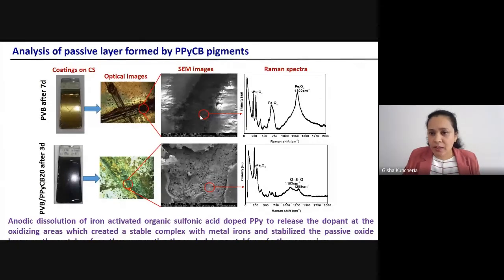Raman spectra show the corrosion product Fe3O4 for the pure coating. But coming to the conducting polymer coating, you can see there is no more Fe3O4 peak, but it shows a new peak that corresponds to the O=S stretching vibration. This O=S is coming from the dopant anion of the conducting polymer, organic sulfonic acid. So this is the way we can analyze whether our coating is giving self-healing protection.